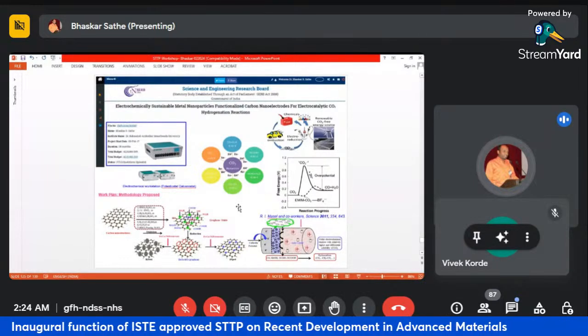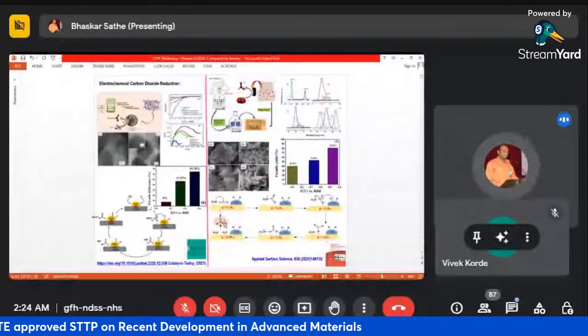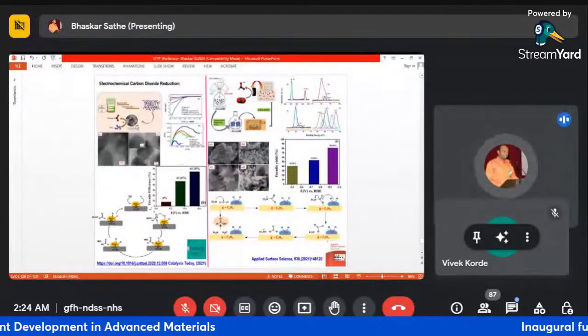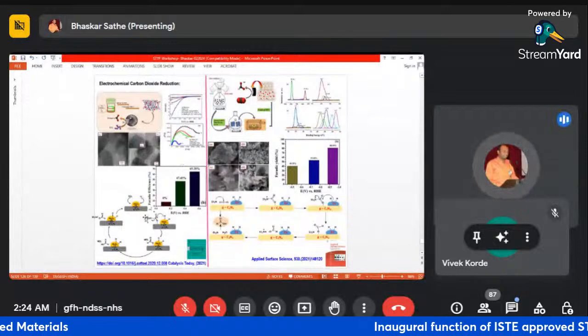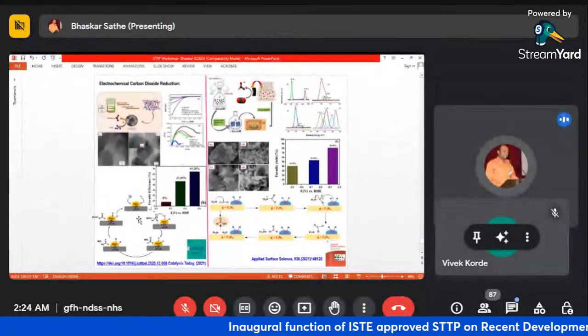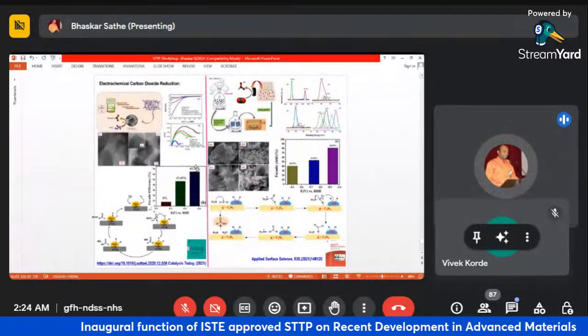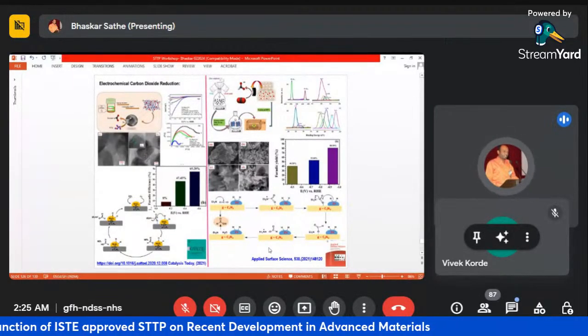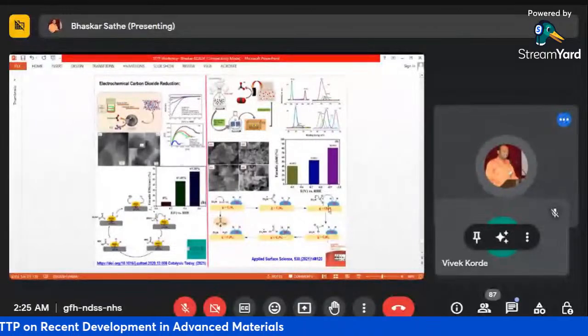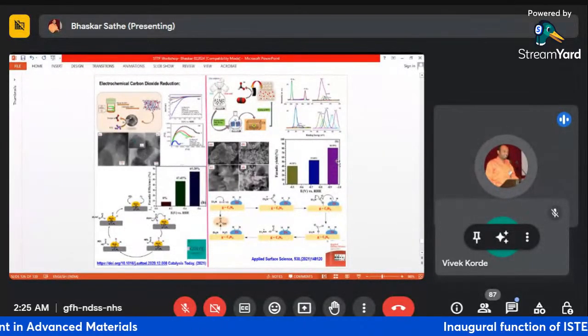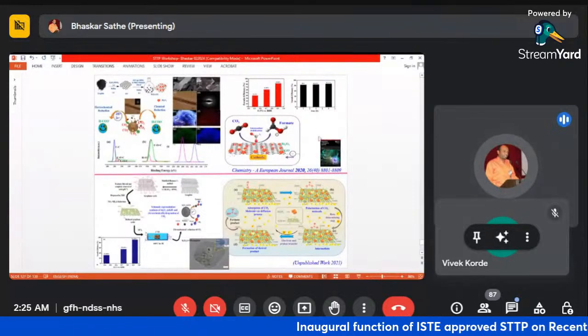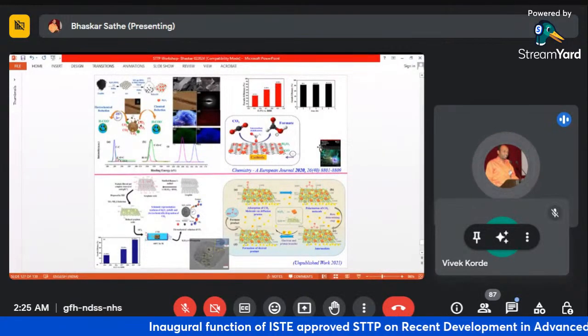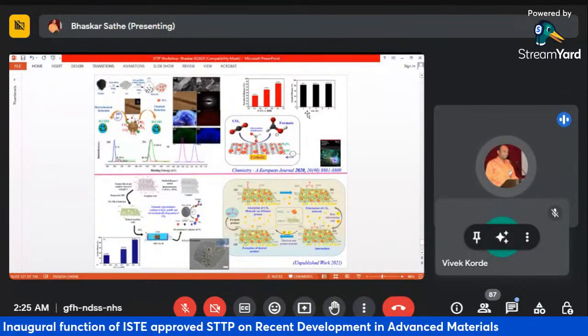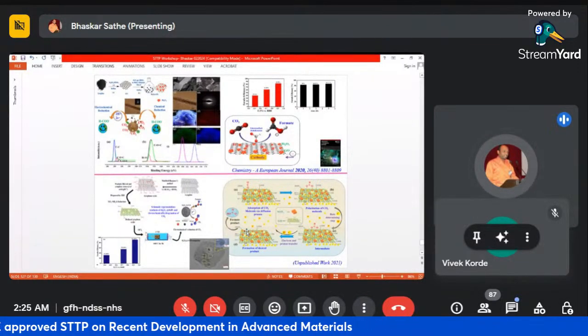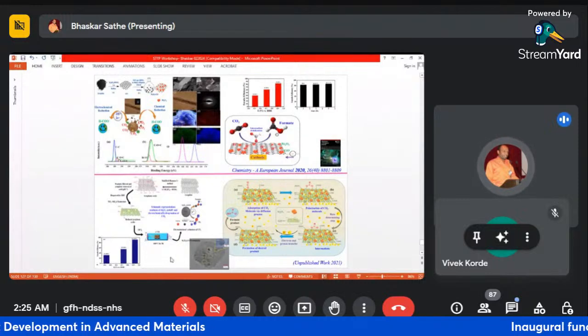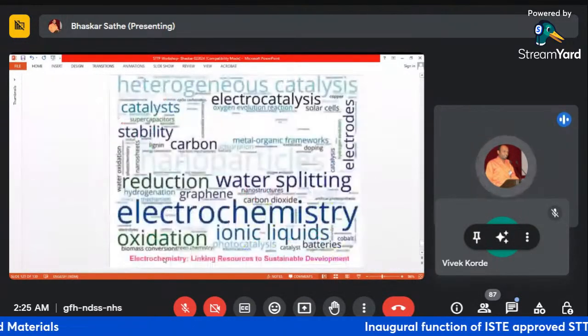In this case we developed different systems, especially electrochemical carbon dioxide reduction on manganese oxide with graphitic nitrogen, where we got around 65% performance. Another system, zinc oxide coupled with carbon nitride, gave a response of up to 89% conversion of carbon dioxide. Other systems like bismuth-based ones reach 91%. An alumina-based system is better; we found 93% conversion.